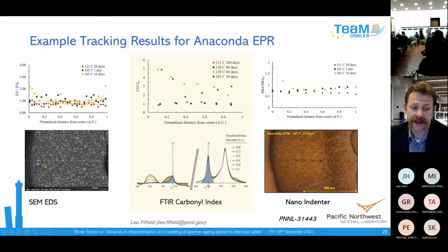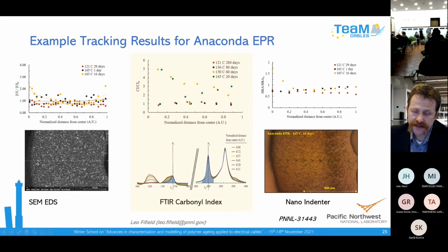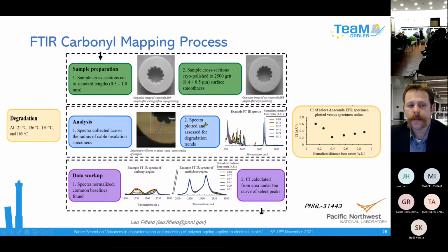In this case, we looked at scanning electron microscopy with energy dispersive spectroscopy to look for oxygen concentration through the surface, and we could see when it was greater at the edges than in the center. We used an FTIR microscope to look at carbonyl index through the thickness, to look at oxidation near the edges. And then we used a technique similar to what's been used in the past to look at mechanical differences across the thickness. We used a nano indenter to look at hardness values throughout the thickness. As the polymer oxidizes, the hardness increases. So we mostly use those techniques to validate our use of color change.